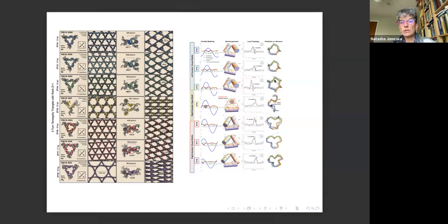And this last column here is the superimposition of our design of the curve, the central strand, with the experimental measurements of the atoms of the structure that was obtained by the lab. For n equal 15, it's similar to n equal 5. There is a crystal, a very two-dimensional crystal in some sense, but you cannot get the triangle, and we can show mathematically that it's just impossible to get the triangle.